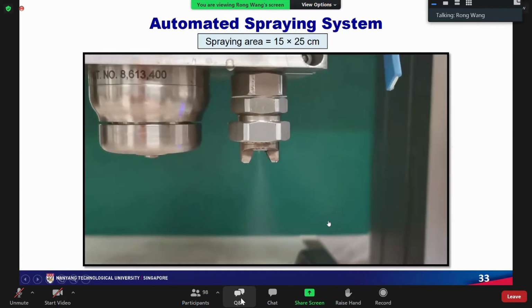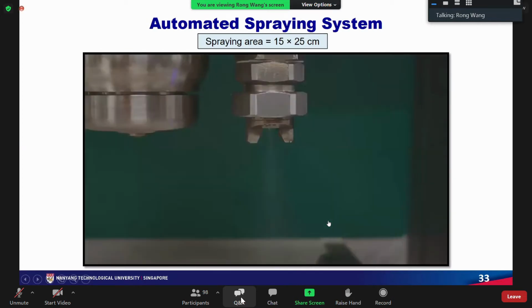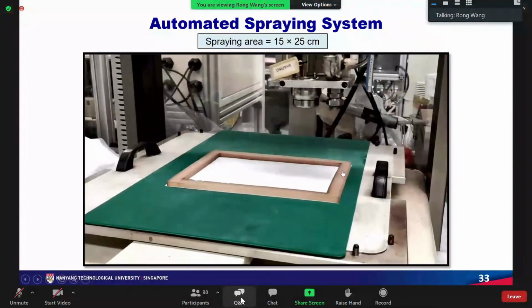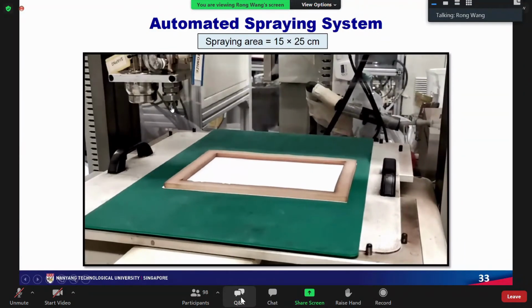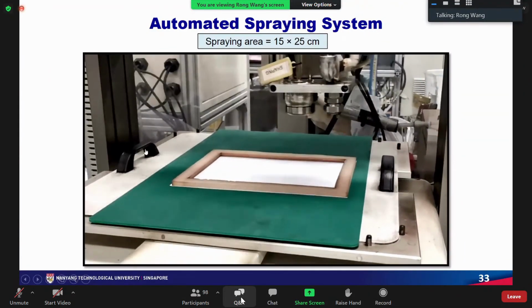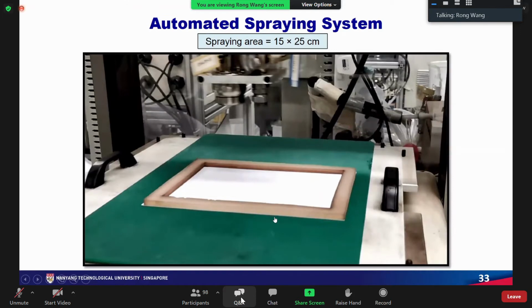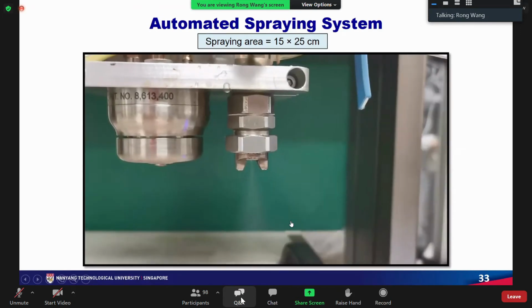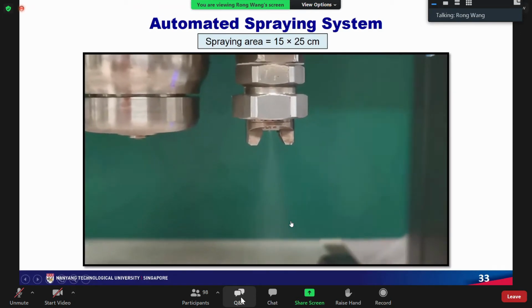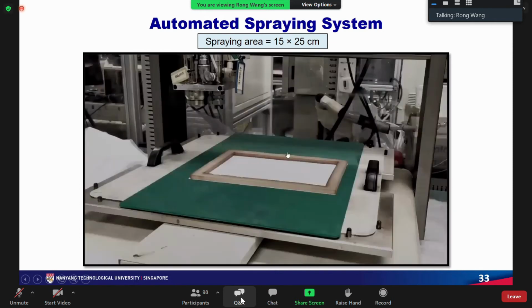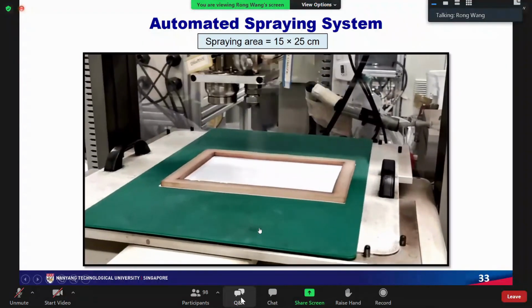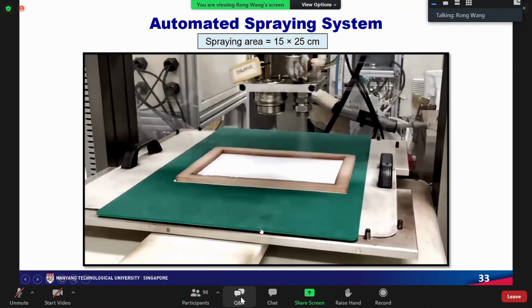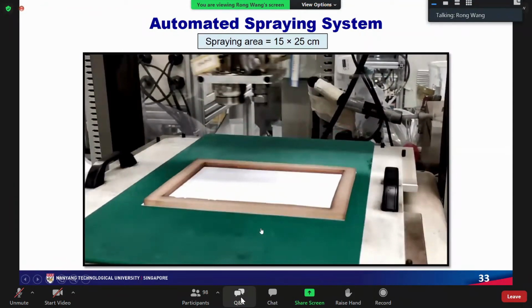Here, we built an automatic spraying machine, the device to do the work. You can see the nozzle spray aquaporin. It moves from the left-hand side to the right-hand side. And also the membrane substrate moves from the front to the end. You can see in this way, we can ensure the coverage of the aquaporin uniformly on the substrate surface.